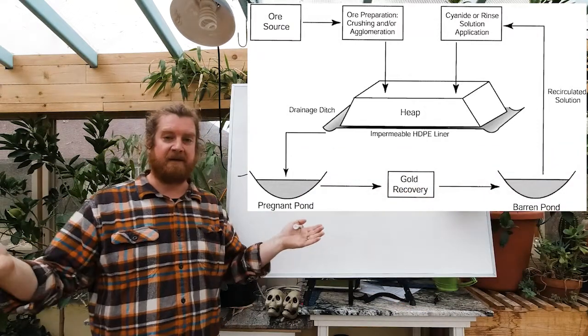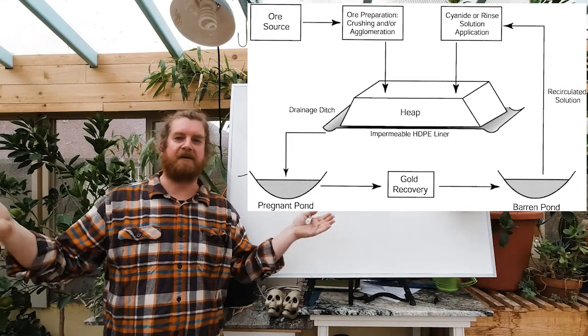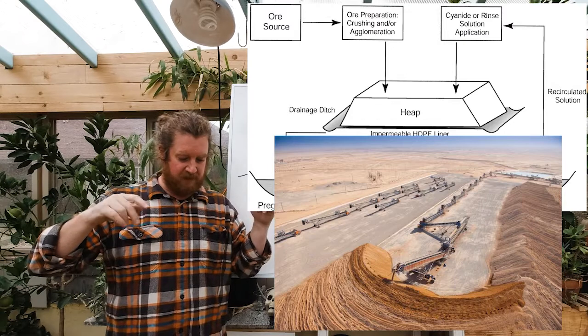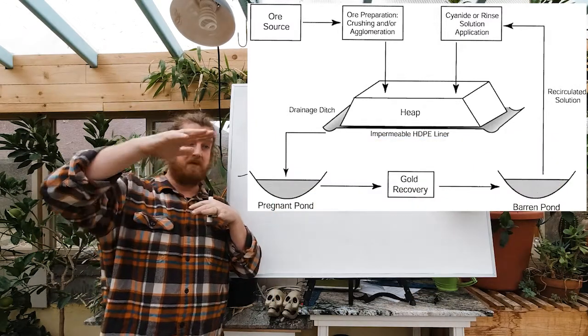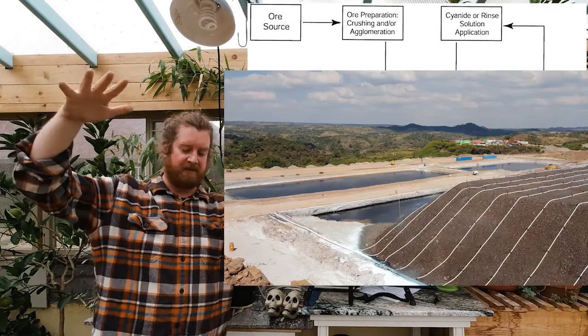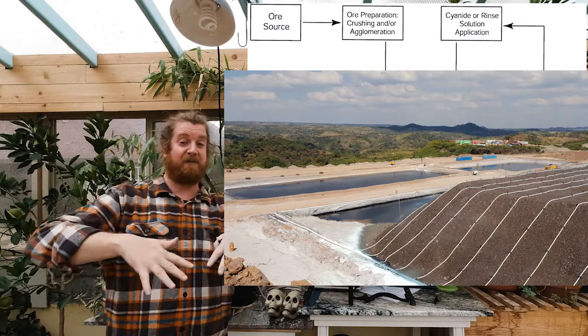It's been used all over Idaho, it's been used all over the world, where we basically take this ore, this powdery, fine-grained sand, and make a big heap of it. Underneath that, we line it with some sort of liner, like a giant rubber pond liner, if you were to simplify it. And then, simplifying, we basically just take a sprinkler system and apply cyanide to that heap, and that cyanide just flows through. Again, we're making coffee, basically.